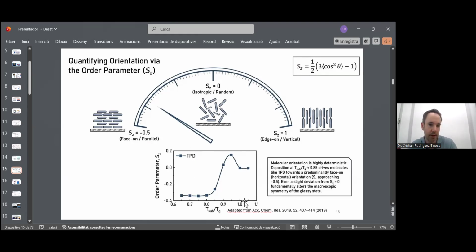With, for example, TPD, an organic molecule typically studied, we see S equal to 0 when we deposit the glass above Tg or at Tg, as expected. Here we have an ordinary glass, with 0 orientation parameter, completely isotropic. But if the substrate temperature is decreased, then we enter a regime where the molecules are slightly oriented in this way, with the molecules perpendicular to the substrate. You see, the magnitude of this parameter is not 1 here, it's 0.15, for example. It means that they are not like this, but they are slightly oriented in that direction.